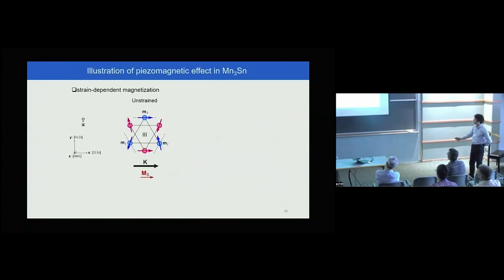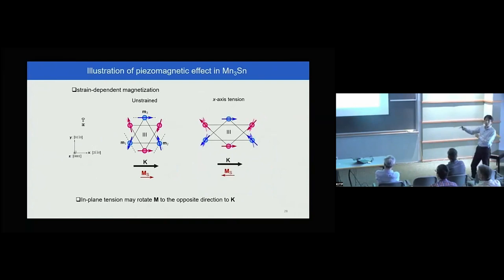So if you have this 120 degrees order anti-chiral texture, magnetization is so tiny, it's almost vanishing. And if you provide tensile stress, it becomes like a ferromagnet, right? So it develops ferromagnetic coupling along this x direction. Because it was originally almost zero, the magnetization itself is canceling each other, just tiny tensile stress is enough to flip the magnetization direction. And having this, the main body of the octopolar state is unchanged. This is a very important point. So the octopolar state is unchanged, but magnetization can be, the tip of the balance can be, tweaked by this small strain. This is the beauty of frustration.